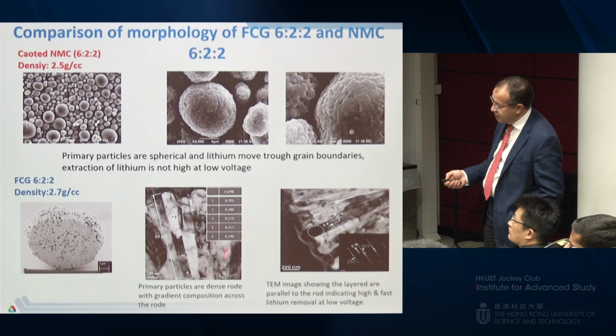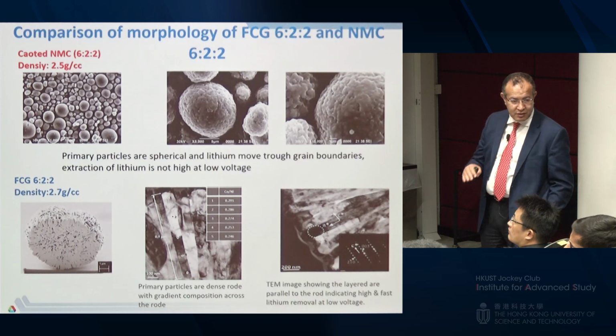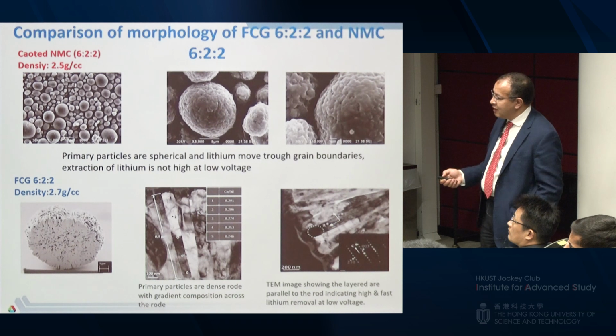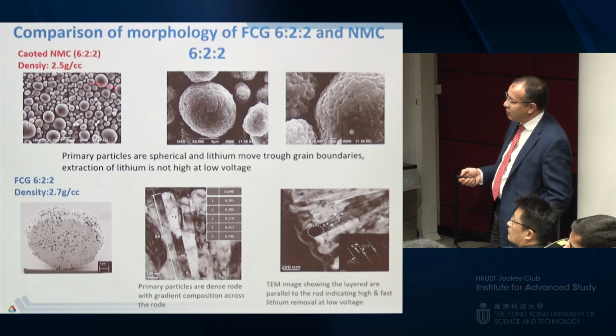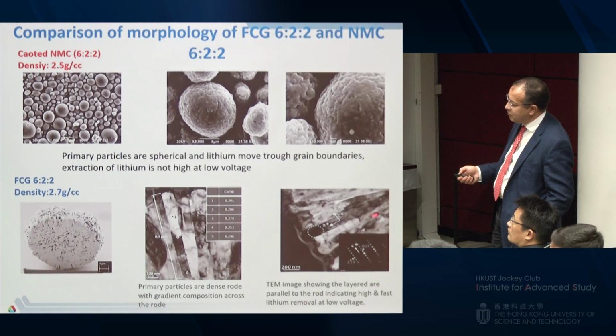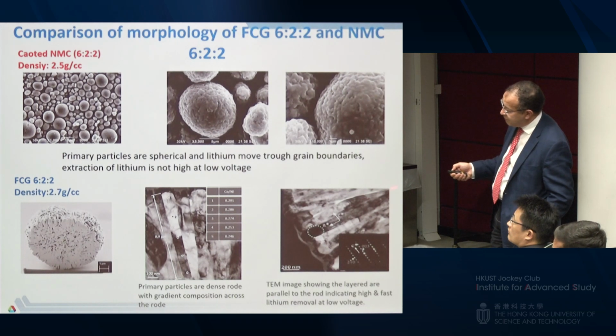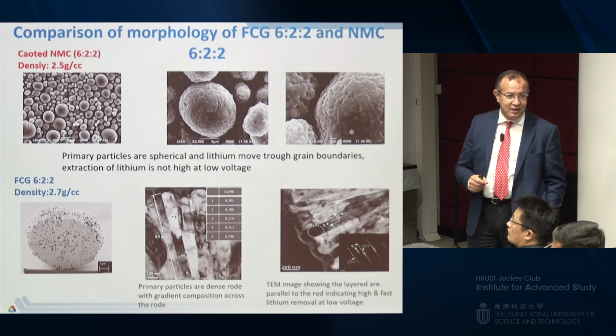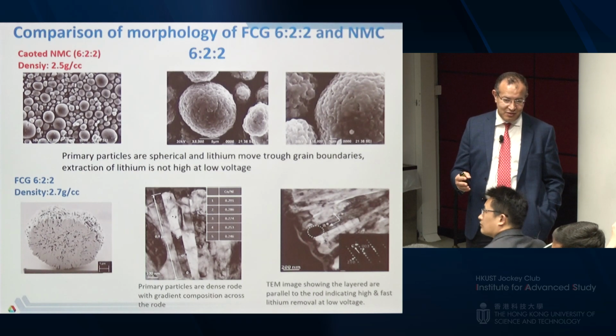If you look at the composition here, it's changing as well. So it's not only at the secondary particle, but the most important thing of all this is this. This is a TEM that shows this rod here, the layers are parallel to the rod, which means lithium will fly out quickly. And that's key to fast charging and discharging of the system.